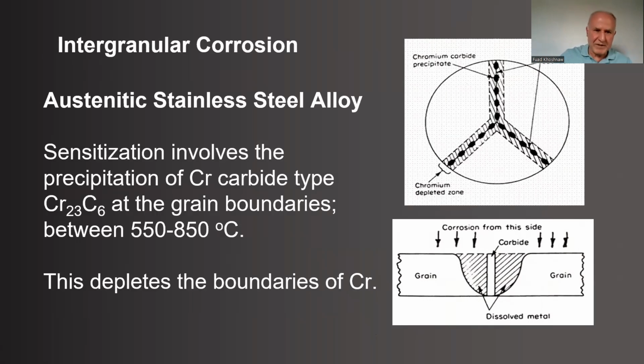This is something that happens in some materials only. For example, austenitic stainless steel, especially 304, and in some aluminum alloys as well. So austenitic stainless steel is austenitic, so one phase, which is good, a homogeneous microstructure. But when it goes through the sensitization temperature, from 550 to 850, it depends from one reference to another, then if the material passes through this range of temperature,